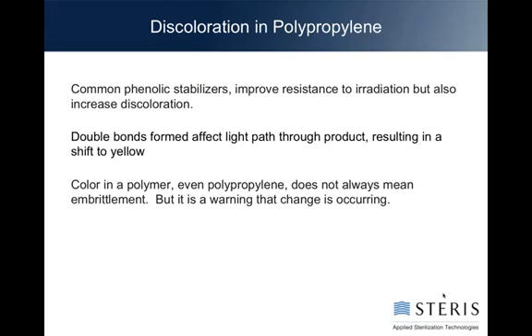Okay. Discoloration. The most common cause of discoloration is a phenolic stabilizer. It's added to improve the resistance to irradiation, but it will discolor. The other effect you're seeing is anything that happens in terms of double bond formation, which is a byproduct of some cross-linkage. It's going to deflect the light passing through it very differently and shift it to the yellow.